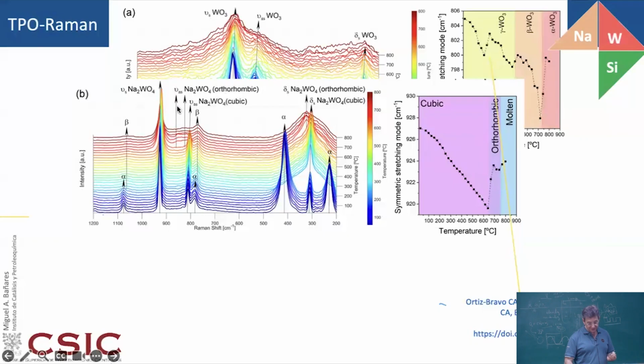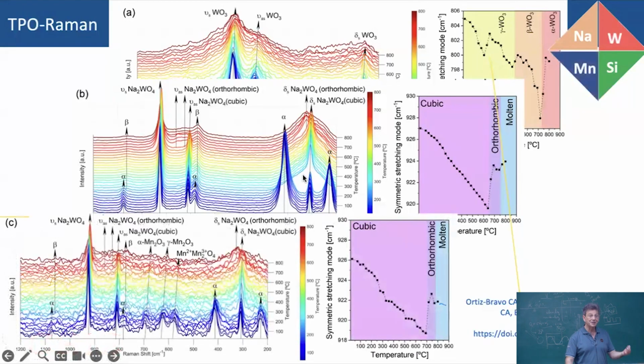When it melts, you still see it in Raman, whereas you cannot see it in X-ray diffraction. You see things, and even sometimes very strange things coming out on the spectra. So something else is happening on the sample, because this broadband is not from the sodium tungstate. This is another story that happens on the support. But we will see it in a moment.